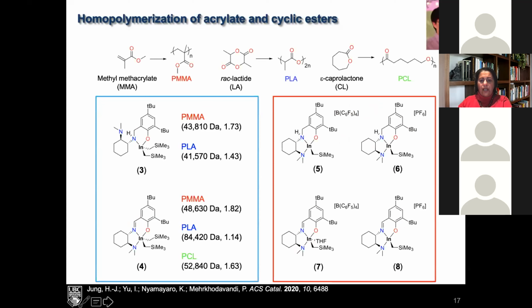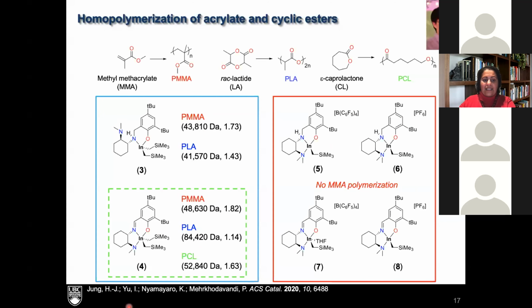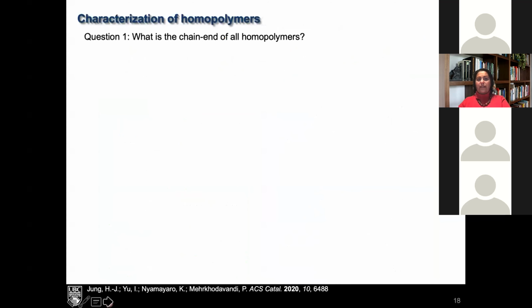And what he showed in this paper was that these systems were not actually active for methyl methacrylate polymerization, the cationic ones. I'll get back to cationic systems a little bit later. The neutral ones were. So this particular system, system 4, for example, was effective for the polymerization of methyl methacrylate, lactide, and caprolactone. And this is exactly the system that we wanted.